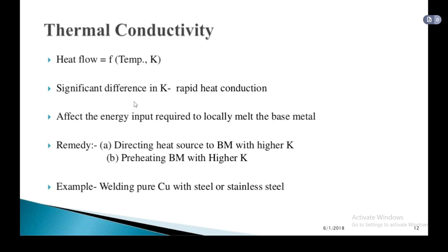So what are the remedies for this purpose? Direct the heat source to the base material which has a higher K, meaning the material with high thermal conductivity. The source of heat will apply the heat directly on that material. Means if there is a joint between the two base materials, the heat source will not be applied at the center, it will be applied towards the base material having a high thermal conductivity.